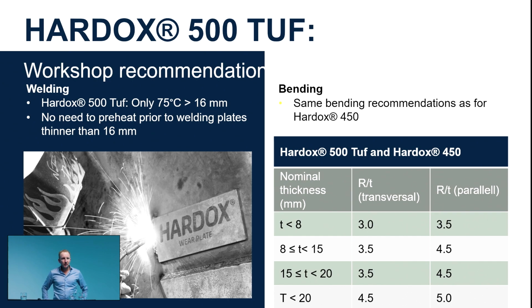When it comes to forming, we have the exact same recommendations for Hardox 500 Tough as for Hardox 450 when it comes to bending. So if you are using Hardox 450 today, you don't need to change anything on the drawings for Hardox 500 Tough when it comes to minimum radiuses. Of course, this material is a little bit harder, which means a little bit higher strength, so you will need a little bit higher force in the bending machine when you form the material.